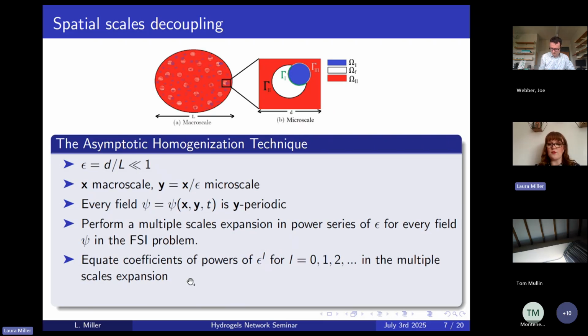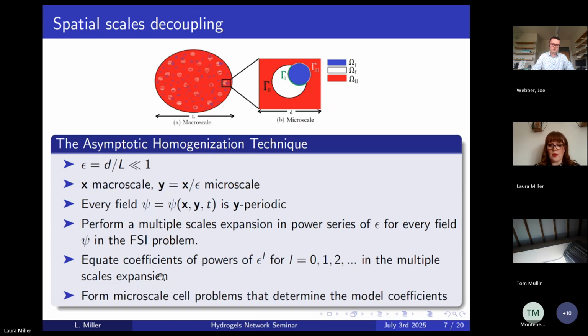And then I can equate the coefficients of different powers of my epsilon. So from powers of epsilon 0, 1, 2, and so on. And you keep equating powers of epsilon and creating closed problems until you close the overall system of PDEs in the end. So from these systems, from these equated coefficients, we form microscale cell problems that are going to allow us to determine the model coefficients. And these microscale cell problems are actually what's going to be remembering the underlying microstructure that we are seeing here once we're back in our full tissue, where we no longer see that there are different subphases or different pore structures or geometries or elastic properties happening at this microscale level.